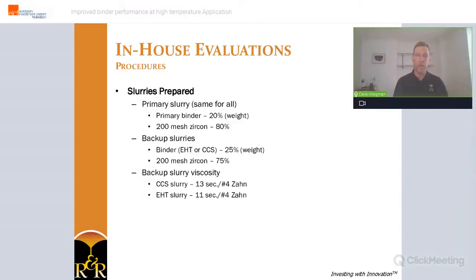Both binders were used to make backup slurries, each with a 200 mesh zircon flour at 75% refractory loading level. The viscosities of the backup slurries were quite different. It was 13 seconds on a Zahn 4 for the CCS slurry and 11 seconds on a Zahn 4 for the EHT slurry. For the primary coating of the test samples, both shared the same prime slurry based on the R&R specialty binder and a 200 mesh zircon at 80% refractory loading.